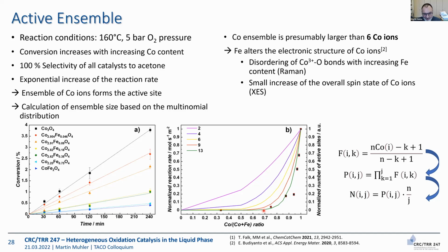Now the question is how to run the reaction in the liquid phase. And again, Tobias Falk had to work quite hard to find conditions where we got some conversion. 160 degrees C and 5 bar of oxygen pressure are actually quite harsh conditions. The reaction is still slow. That means it's running, as you see here, for 4 hours. And during 4 hours, conversion is still low, just up to 4%. But we do get